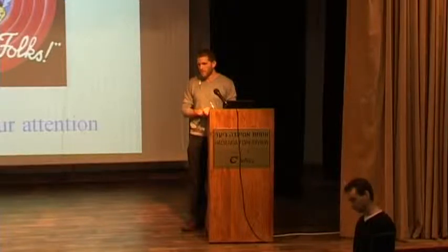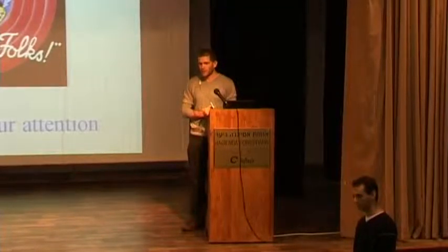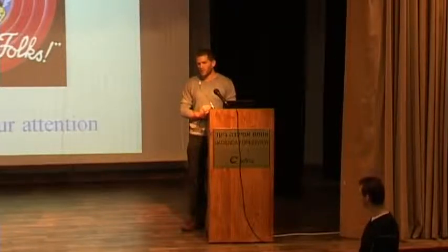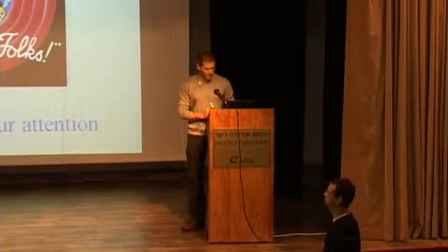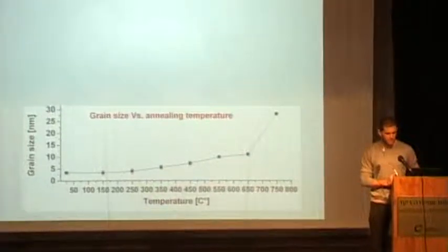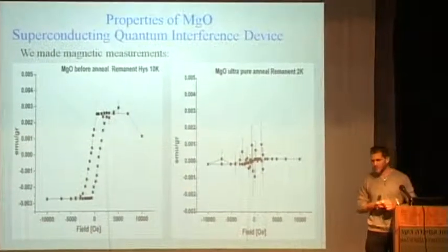You only have those magnetic properties when you cool? Yeah. In room temperature, you can't see any ferromagnetic behavior. Usually, it disappears at about 150 Kelvin. Okay. You have to distinguish between the annealing temperature and the temperature of appearance of ferromagnetism. Now, there's a sort of a Curie temperature around 150. Yeah.